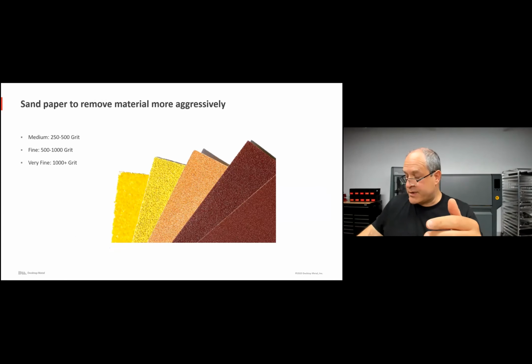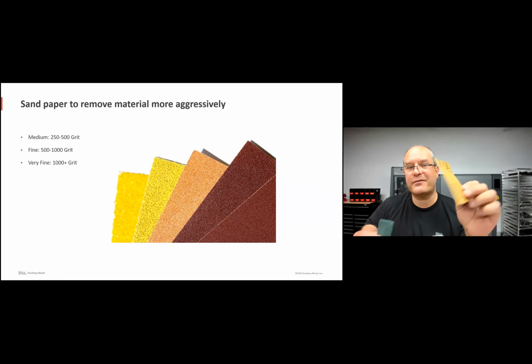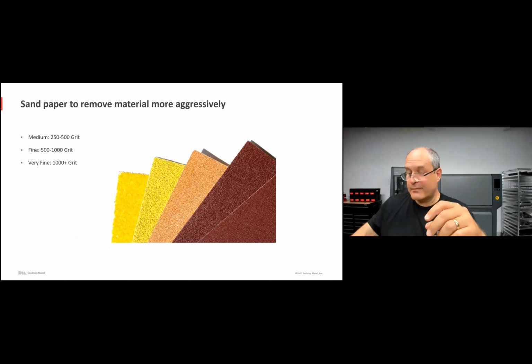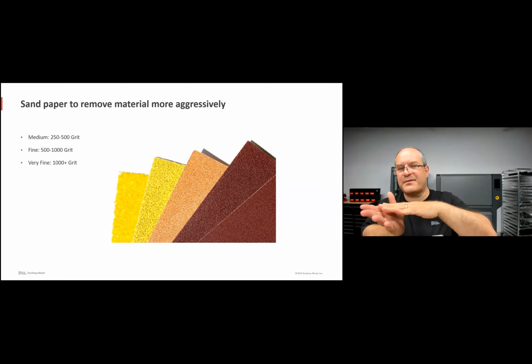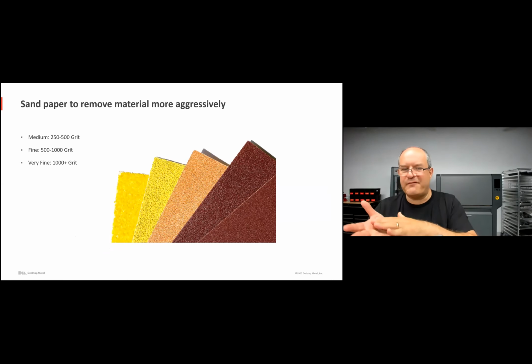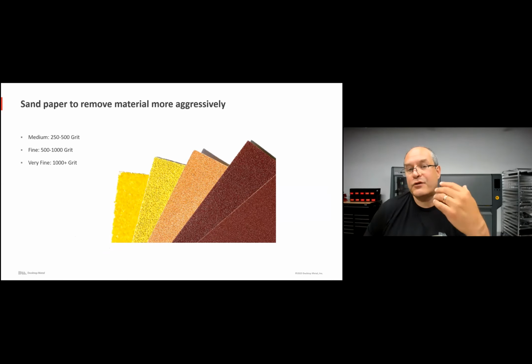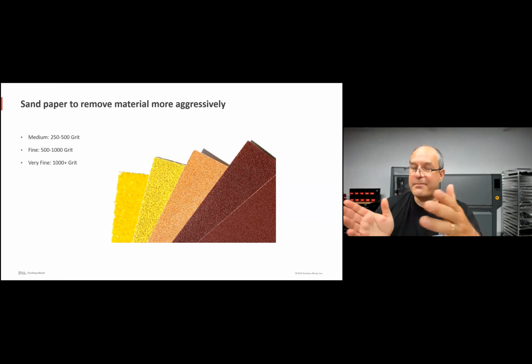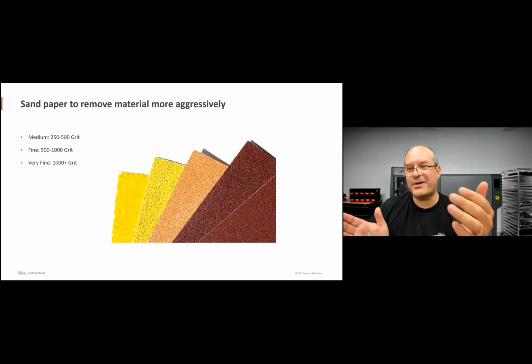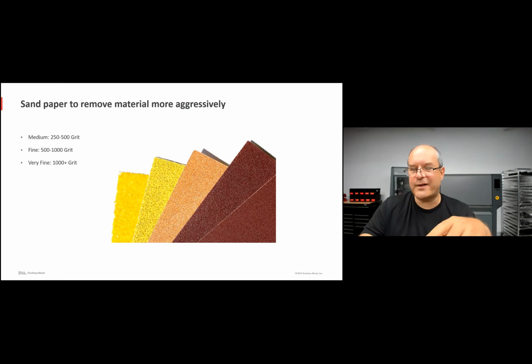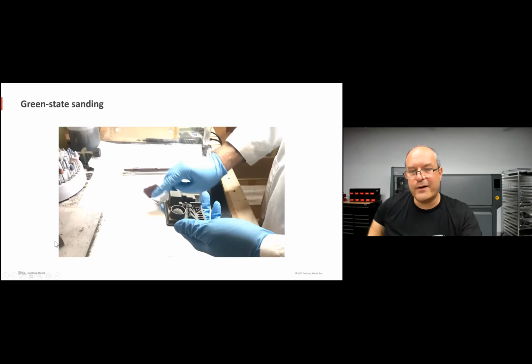And then you can use sandpaper in a variety of grits, and you might progressively go initially with a medium grit, then fine, very fine, to really smooth out. It really depends on how much you want to get rid of. And the trade-off here is sandpaper can get rid of the material pretty aggressively, so you actually want to be kind of light with how much you use it. Here's a little video.